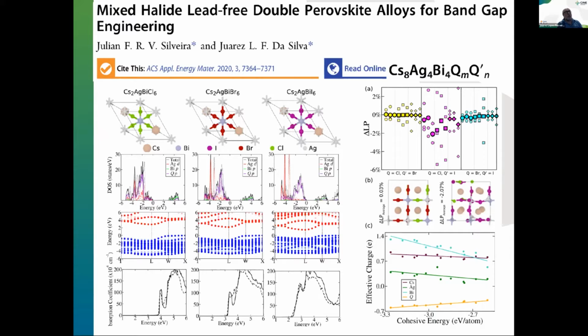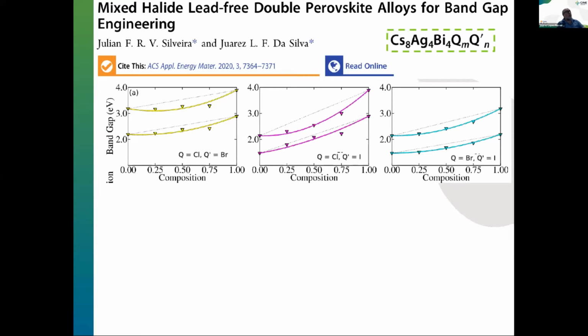Here you can see the cohesive energy with respect to the effective charge, which shows what is driving the stability of those systems. And here I show the band gap. In figure A, the first one is when they combine chlorine with bromine, and you can see the evolution of the band gap when you create the alloy, which is expected and is a well-known behavior for alloys in the semiconductor business. Then you move on to chlorine, iodine, and so on.